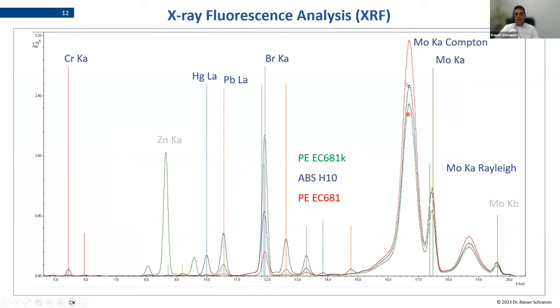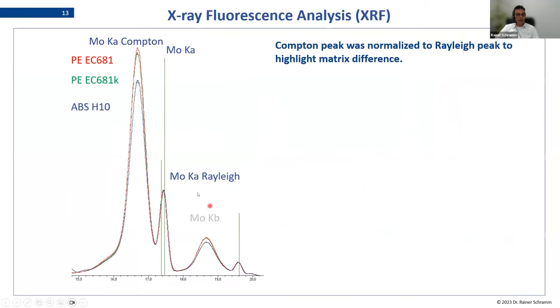And you can see how this scattering signal is varying depending on the sample. And to see now the matrix effect, I need to normalize these spectra to the Rayleigh peak. And this would then look like this. And then you see that the two PE samples have more or less the same Compton peak, and the ABS has a different one. So that means if you would take the intensities of your trace elements in such a polymer and you just divide it by this peak, you make a kind of matrix correction, and you could calibrate elements in ABS together with elements in PE.